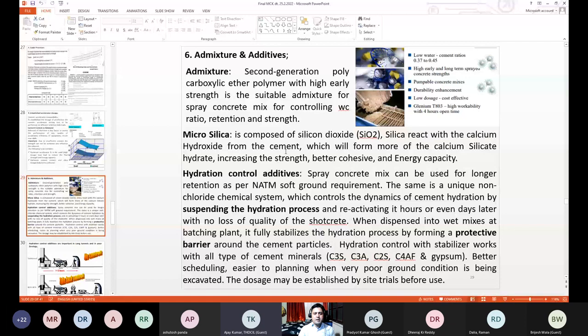Hydration control additive in spray concrete mix can be used for longer retention as per NATM soft ground requirement. The HCA is a unique non-chloride chemical system which controls the dynamics of cement hydration by suspending the hydration process and reactivating it hours or even days later with no loss of quality of the shotcrete. When dispensed into the mix at the batching plant, it fully stabilizes the hydration process by forming a protective barrier around the cement particles. Hydration control stabilizer works with all types of cement material, C3S, C3A, C2S. It allows better scheduling and easier planning.